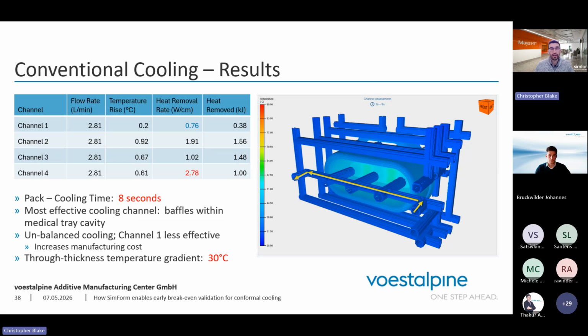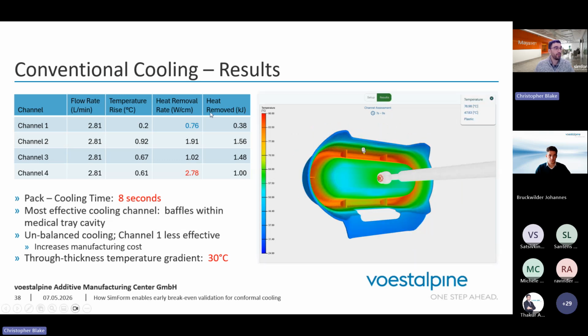So having extra channels is actually going to increase the manufacturing costs here. So what we can do is use these simulations to decide, okay, do we actually need some of these channels, or can we save on some of the manufacturing process? Another important thing to note is in certain locations, we're actually seeing a through thickness temperature gradient as high as 30 degrees Celsius, just because we can't get cooling into this narrow cavity of the part. And so this is going to, as we'll see later, result in some additional